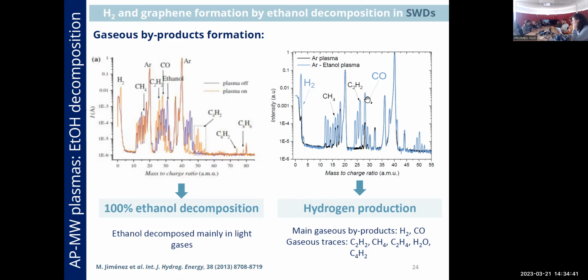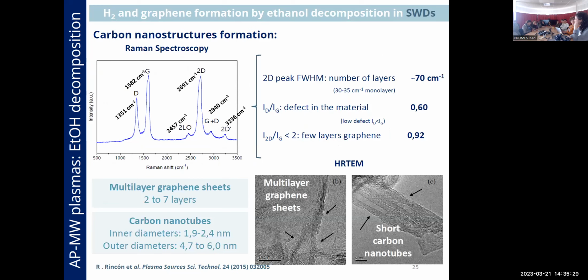Another gas that we are obtaining by the decomposition of ethanol is carbon monoxide. These are the two most important gaseous byproducts obtained by the decomposition of ethanol. However, there are also some other gases, which are acetylene, methane, ethylene, and diacetylene. I remark on that because we will see later on that the way the ethanol is decomposed, favoring the production of some hydrocarbons or others, will be very important to understand the formation of carbon nanostructures. So, as I said before, these are the gaseous byproducts that we obtain, but we are also obtaining solid material. It's very black. So at the beginning, we thought, okay, it's carbon coming from the ethanol.